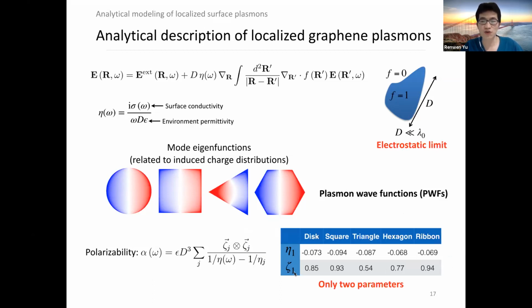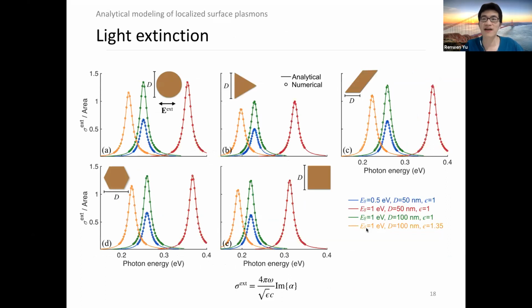And with only these two parameters, we can do a benchmark calculation to compare our semi-analytical model with fully numerical calculations. As you can see, no matter what the doping level is, no matter what the lateral size of the nanostructure is, and no matter what the permittivity of the environment is, our semi-analytical model matches very well with the numerical results. And I would like to mention that all these calculations take less than 1 minute, all of them. So that means it's a very efficient method.